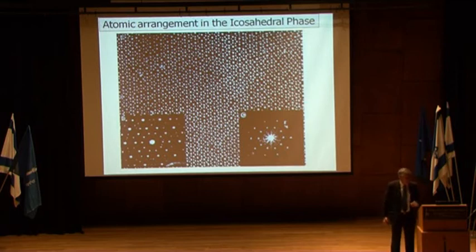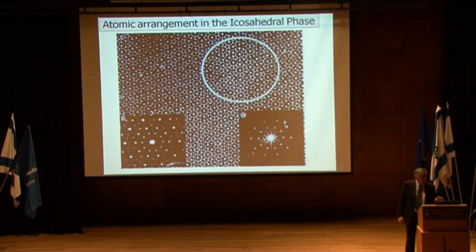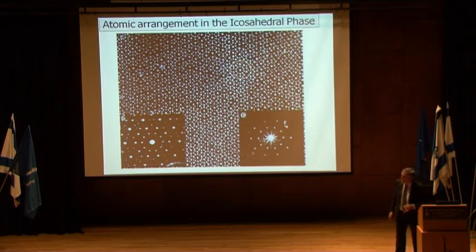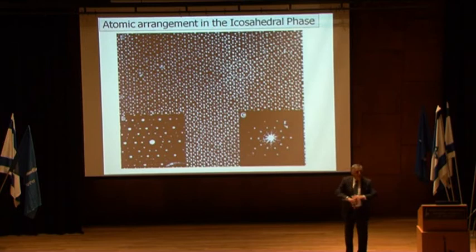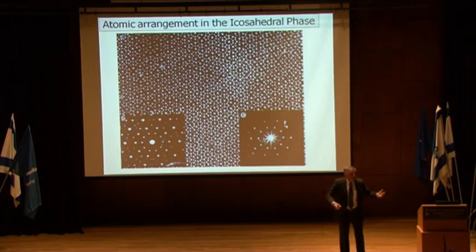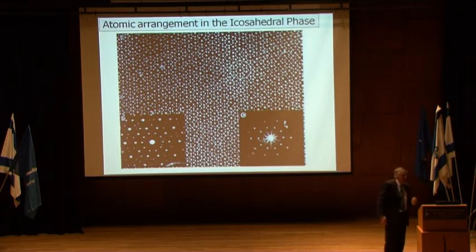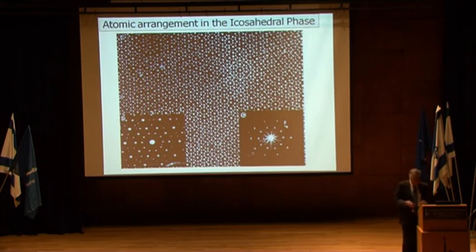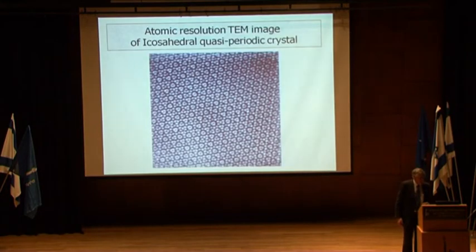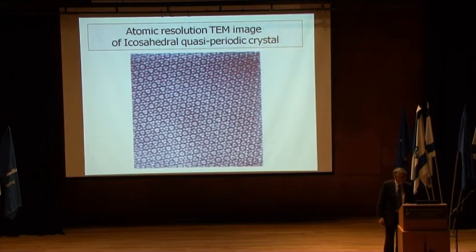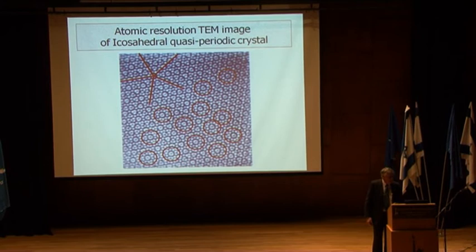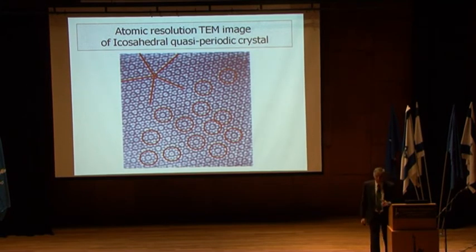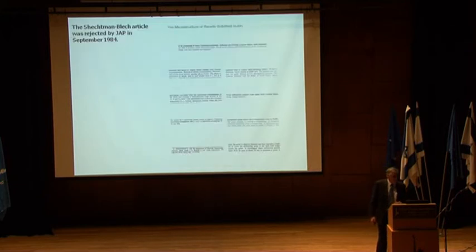Nowadays, you can do this by computer. You can take and select a small area, and then make it smaller and smaller, and shine the laser beam only in that area. And when that area becomes smaller and smaller, this diffraction pattern doesn't change. It will disappear for lack of information, but it doesn't change. That means that, hey, this 5-fold rotational symmetry is really a property of the material itself, and not a combination of anything else, periodic. And this is a modern picture of quasi-periodic material, and you can see all these motifs arranged in a quasi-periodic way. I will talk shortly about quasi-periodicity. You will all understand it very well.